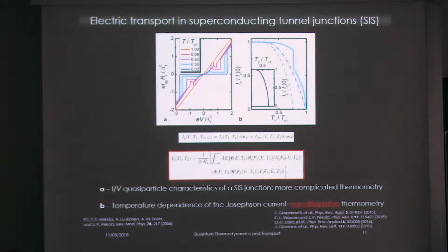The same can be done with fully superconducting tunnel junctions, taking advantage of the SIS junction. There are two modes of operation. One is by exploiting the strong feature appearing in the quasi-particle current of an SIS junction. This is the well-known quasi-particle current. You see these peaks come out. These are the logarithmic singularities appearing at the difference of the gaps of the two superconductors composing the junction. So one can take advantage of this very sharp structure to make thermometry.